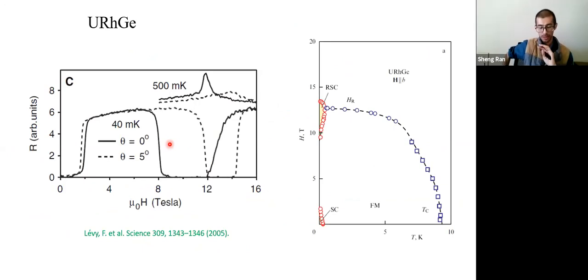And there's another similar case, uranium rhodium germanium. This is one of the ferromagnetic superconductors. So for uranium rhodium germanium, again, you have superconductivity and it goes to normal state and goes to superconducting state again. And here, people believe ferromagnetic fluctuation is playing a role for this field-induced superconductivity.